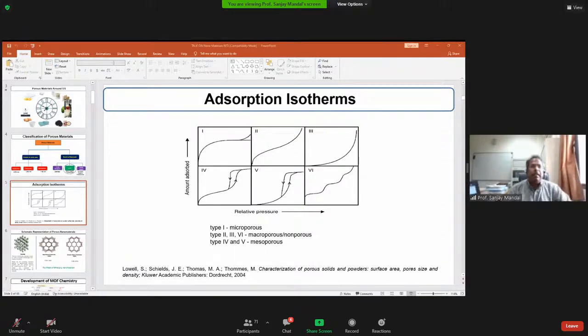In measuring their BET surface area, the International Union of Pure and Applied Chemistry has defined type 1, type 2, type 3, all the way to type 6. And you can see type 1, when you have this kind of curve, you get to see microporous. On the other hand, type 4 and type 5, which are mesoporous, also have something called a hysteresis loop. That means their adsorption and desorption don't come on the same line.